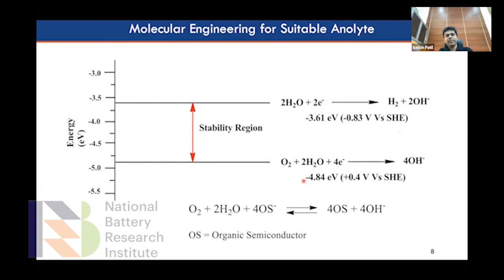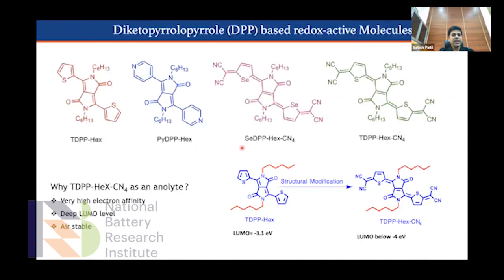So it's important that we generate new materials. As I said, we have a large variety of materials, but the material needs to meet this criteria of a stability window. We recently worked on a variety of donor-acceptor polymers. In our group, we have been working on this donor, a thiophene, and the DPP lactam ring as an acceptor. Then we have these donor-acceptor structures, and we can play with this window. We can change from thiophene to pyridine to selenium, and you can also introduce nitrile groups. And you can introduce a variety of different alkyl chains on this nitrogen.